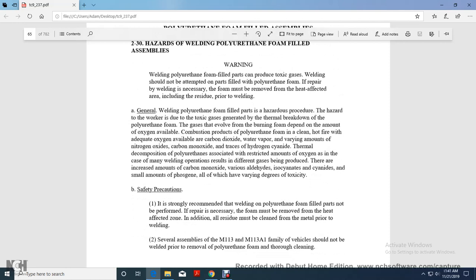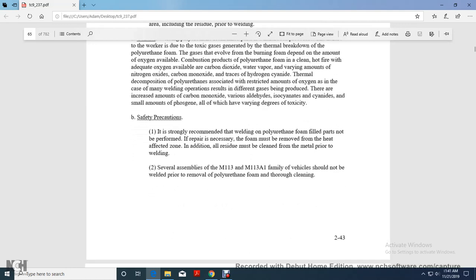The hazard of this work is due to the toxic gas generated by the thermal breakdown of the polyurethane foam. The gas produced from burning the foam depends on the amount of oxygen available. When polyurethane foam burns in a hot fire with adequate oxygen, the products are carbon dioxide, water vapor, nitrogen oxides, carbon monoxide, and traces of hydrogen cyanide. With thermal decomposition of polyurethane under a restricted amount of oxygen, as in a welding operation, different gases are produced. There are increased amounts of carbon monoxide, various aldehydes, isocyanates, and cyanides, with small amounts of phosgene, and these have varying degrees of toxicity.